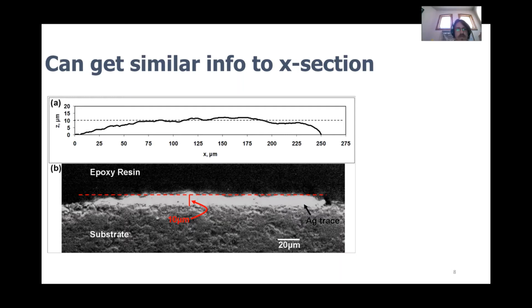But there is an article that I was struggling to get published as a PhD student because the reviewer didn't believe my profilometry data. So I made this SEM cross-section and proved that the maximum height of roughly 10 microns that I got off the profilometer correlated well with what you would measure off of an SEM. So you can get similar information to a SEM cross-section with a profilometer. In my mind, it's still a pretty good instrument.